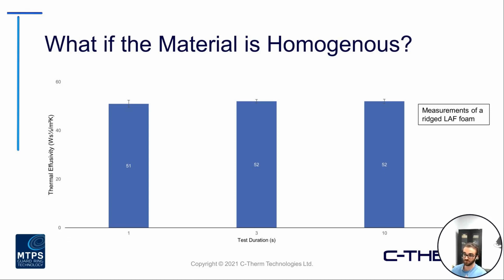Again, if it's homogeneous, there's no layered structure to it. You can see very comparable results, essentially no difference based on the sample that is tested. So again, understanding what type of sample you're testing and how you're testing it is going to be really important to really pull out those bits of value that you're getting from these thermal measurements.